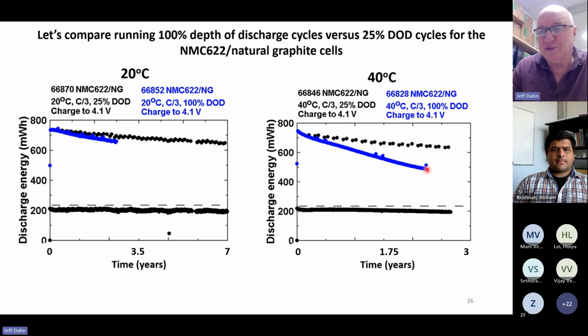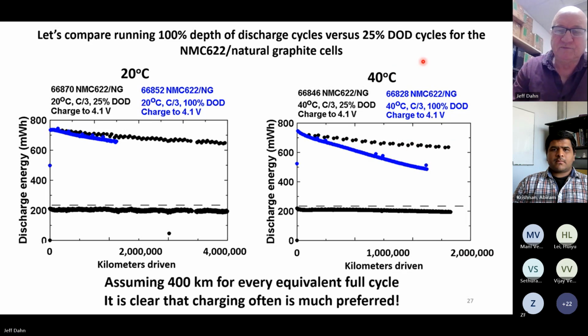And the difference is much, much greater if the cells are tested at 40 degrees C. Here it's only out to 3 years, and you can see that the cells going 100% DOD are declining pretty fast compared to 25%. If you wanted to know how long this could drive your vehicle, 4 million kilometers at room temperature, 2 million kilometers at 40 degrees, and with still lots of battery life left. So it's pretty amazing.